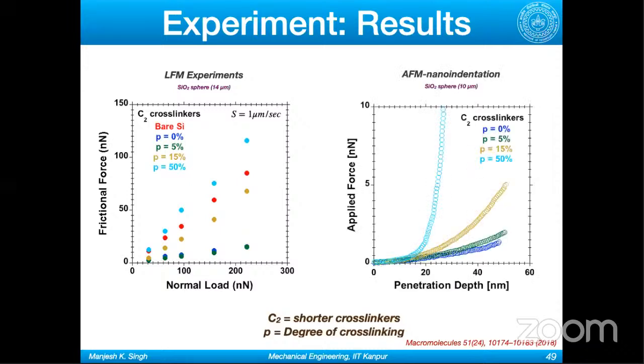We also did this AFM-based nano-indentation curve, again with the colloidal sphere attached to the tipless cantilever. People use it to get the modulus as well, which I would like to avoid, because I would not like to believe AFM data to tell me the exact magnitude of the modulus, because we don't know exactly the contact point and other complications involved. But what it can tell you for sure is which one is softer and which one is stiffer.